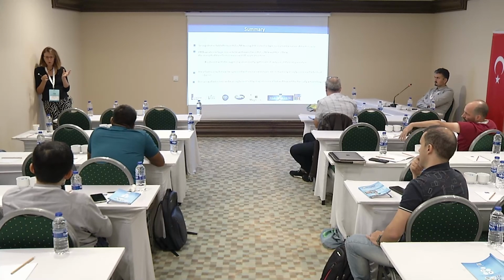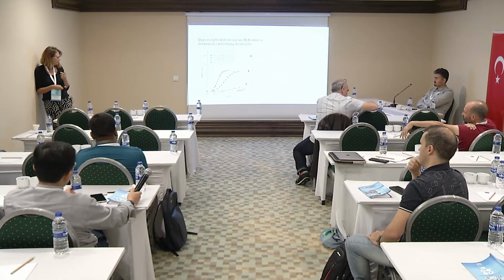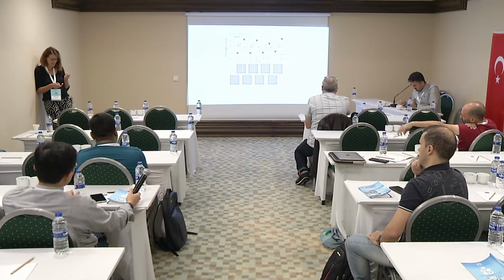Right, and that may also lead to some irreversibility. It's sometimes hard to get 100% reversibility. They're largely reversible, but it's very difficult to have 100%. But that we don't really know. I suppose there must be some charging at some interface, so that if you call it reversible with the same voltage, no. But reversible in the sense that we can go back to the same state, but with a different time or a different voltage. Actually, I think I have a slide. Yeah, so you see the reversibility.